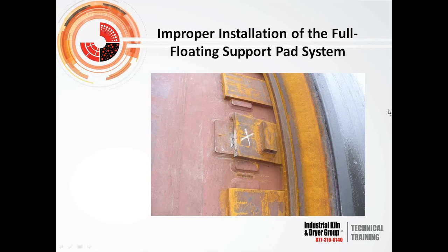And John, the other thing we wanted to illustrate here is that on the sides of the tires, you'll get the tire pads wearing into the side of the tire. And a lot of people think the solution to that is to skew your rollers differently, but it really isn't. This problem is generally remedied by getting the slope of the base on line in the proper position so that you don't get tire block wear. So it's important that you have your bases and rollers on the correct slope. So you might want to reroute your bases and check out the slope.